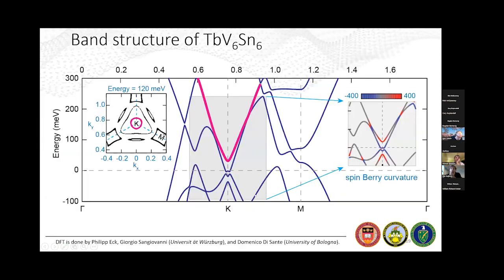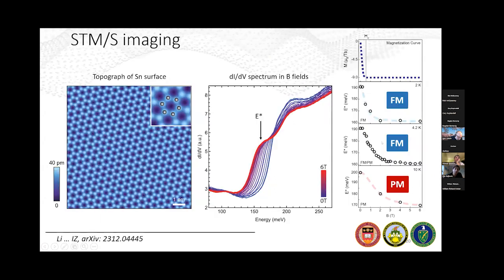So this is what the electronic band structure looks like here. With the help of our theory collaborators, we were able to calculate the spin Berry curvature of different bands. Similarly to what you get in a simple case for a single Dirac dispersion, we have large Berry curvature concentrated at very special points.